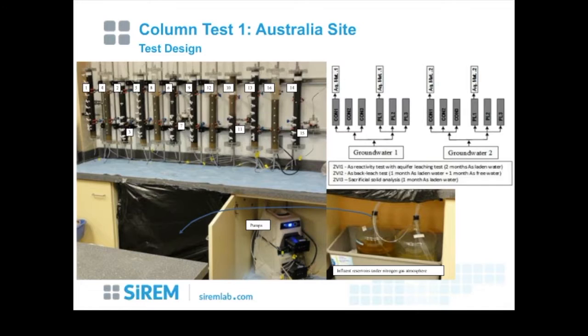So in this case here, we're looking at the column with groundwater 2. This is the column with groundwater 1 and then groundwater 2. Column 1, which is this one here, was a ZVI to aquifer sequence, and this allowed us to get information about arsenic removal capacity and if the arsenic would be mobilized down gradient, because we took the effluent from the zero valent iron column and put it through just an aquifer matrix column to see if the water coming off of that potential barrier would then strip any arsenic out of there.